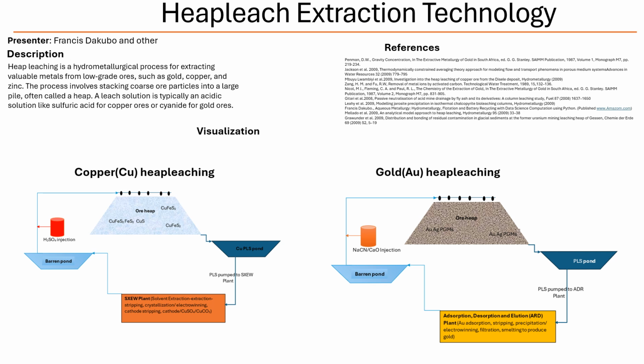But with the agglomerated ore. Ah, the agglomeration makes a difference. A huge difference. They got much better gold extraction, 86%, because the agglomerated ore allowed for better solution and airflow, a fully well-mixed solution, 10% airspace, and no dead zones. Agglomeration is like creating highways for the solution to travel through the heap. You got it.